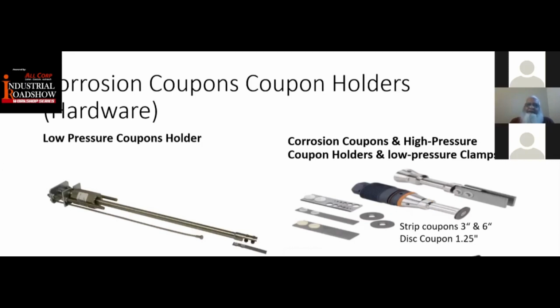And these are the actual clamps which are fitted to these devices as a safety measure, because these devices have a seal in there. If the seal leaks, these probes can be pushed out. So in order to protect these probes from this unacceptable escape, we always install these clamps, low pressure clamps, to hold the probes in place.